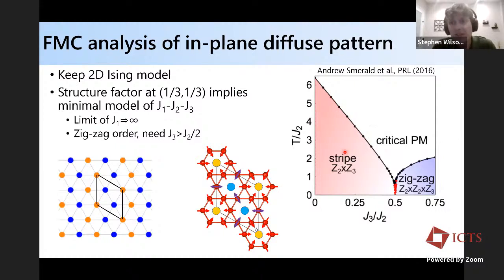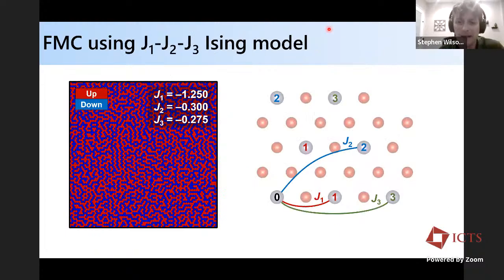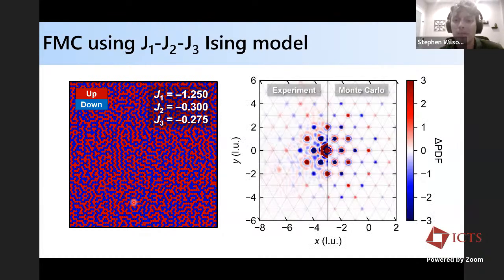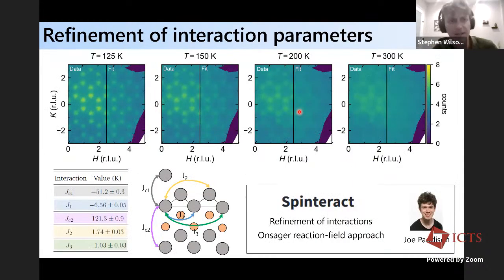And then you can also do a forward Monte Carlo analysis. If you think about a triangular lattice, the wave vector is at a third, which means we need some zigzag phase. If we assume a minimal model of J1, J2, J3 for a triangular lattice, and we take the limit where you have large J1, then we should have some constraints in terms of J3 having to be appreciable enough. Using a forward Monte Carlo model, one can capture the same type of behavior using the zigzag, again using this J1, J2, J3 model. And one can capture the delta PDF pattern as well as the structure factor in these triangles, okay?